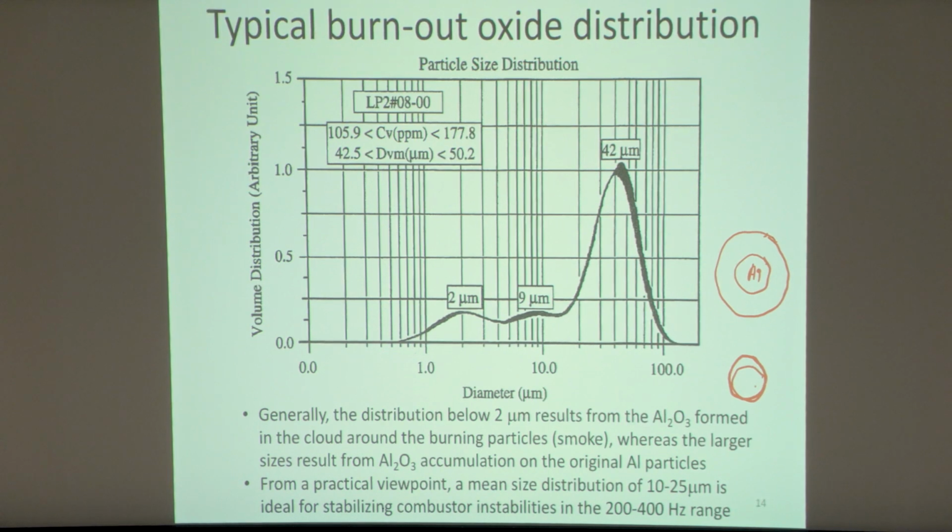And what you'll note is there's a size range that's 2 micron and below, and then there's another size range that's quite a bit larger. So typically, at least, you find a bimodal size range. And the bimodal size range could be coming from two factors, right? It could be the particles forming out here are initially nanometer in size.